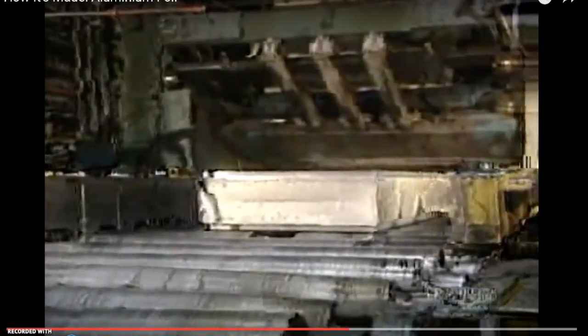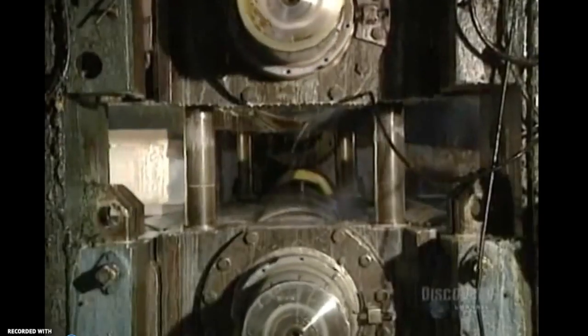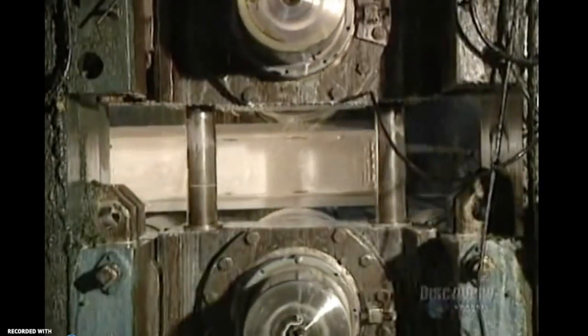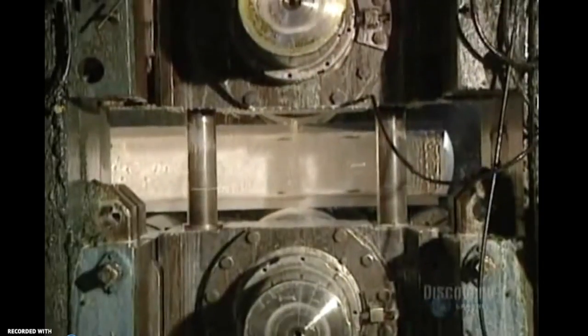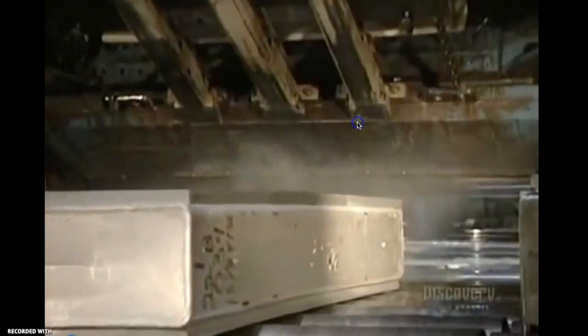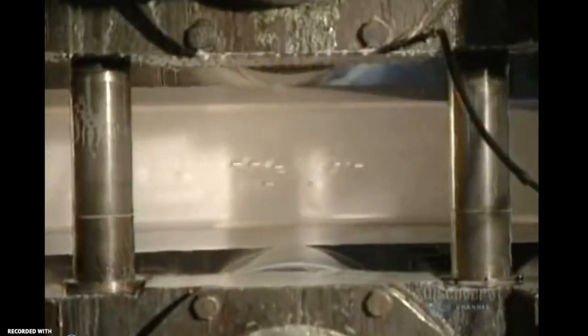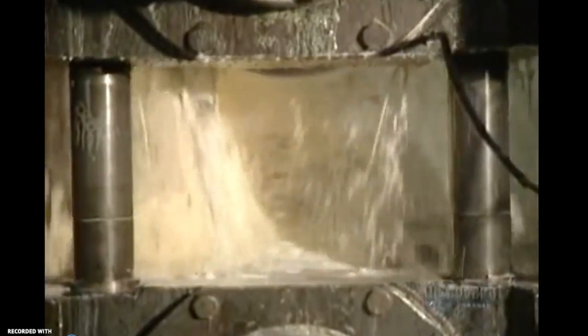The many steps in the thinning of the ingot begins. The aluminum block is crushed by the hot mill rollers. Temperatures in the rollers are between 455 and 540 degrees centigrade. Pressure on the ingot is continually verified by a technician. If too great, it's lowered and the technician then adjusts the pressure. The heat is so high that the ingot risks sticking to the mill's roller. To prevent this, everything is cooled with a liquid that's 95% water and 5% oil.